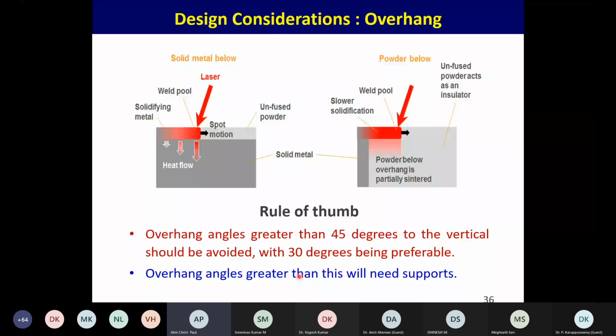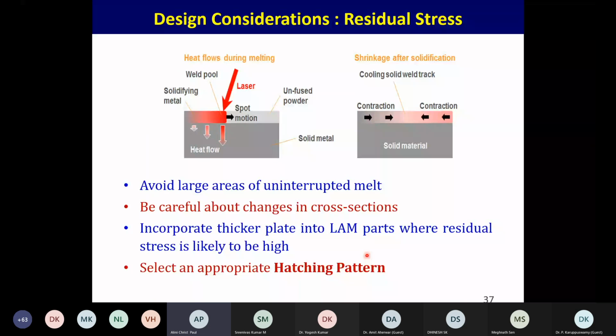And whenever you have a geometry in which these things are not easy to remove or very difficult to reach, then we need to come up with some support structure to make the part in a different way. Another aspect is that we are melting and depositing material. Whenever the material is melted, it expands naturally, and the moment it becomes liquid, the old stresses go away, and after that the contraction starts. This leads to residual stresses in the material, and different hatching patterns result in different residual stresses. If at any point local residual stress is more than the ultimate tensile strength of the material, it is likely to have cracks. So we have to take care while considering the design.